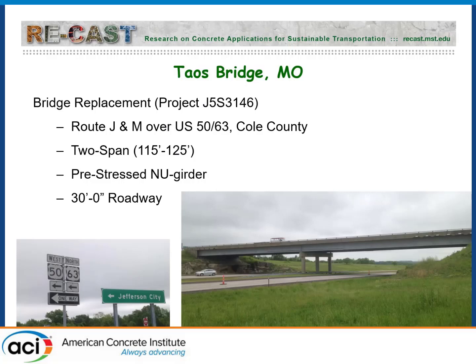So we got a bridge that was actually quite challenging with two spans that are quite long. You see here the lengths of the spans, 115, 125, simply supported on pre-stressed girders with the bridge deck being 12 inches with double rebars continuous. So as you would expect in the middle, here is the bend, you'll expect a lot of negative moment with the concrete being in tension. And we had to take special measures to reduce the shrinkage of the concrete, but also when cracking does occur, to keep the cracks very, very small.